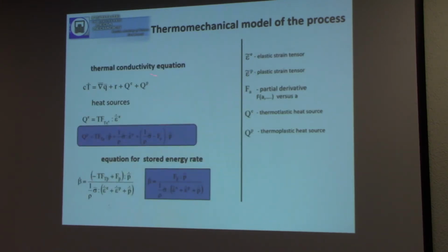If we continue, we can write a well-known thermal conductivity equation with two sources, a thermoelastic and a thermoplastic source, and we have to determine the structural sensitive variables. It is quite easy to write the well-known equation of stored energy rate. And here you can see the coupling between the temperature and structure. Generally, again at a bifurcation point, we can avoid the coupling between temperature and the structural fraction, and practically we directly connect the stored energy and the thermodynamic potential.